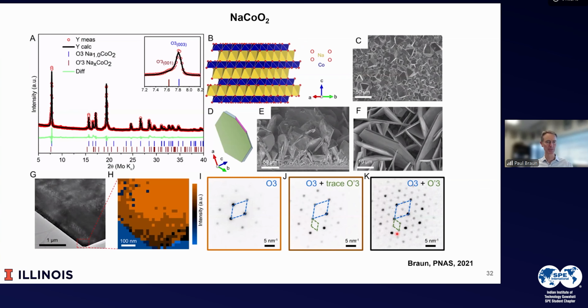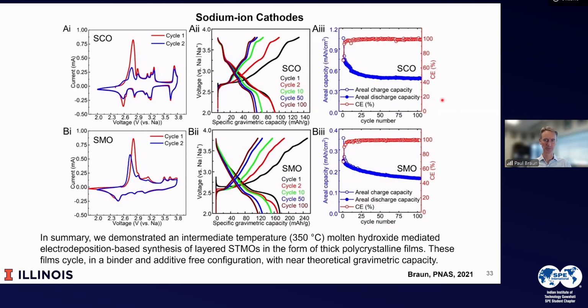If we just look a little bit about the sodium cobalt oxide, because we can directly compare this to our lithium cobalt oxide, it's quite similar. It's primarily O3 with a small amount of O'3. It doesn't grow quite as dense, although we haven't worked as hard. You can see that there's these platelets. The O3 planes make up the faces of the platelets pretty much as expected. And giving examples of the cycling, here is the sodium cobalt oxide. It does fade and then becomes quite stable. Coulombic efficiency is reasonably good. The sodium manganese oxide has sort of a slow and continuous fade due to phase changes. So I would argue that if the sodium systems are of interest, there's still some additional work to do.